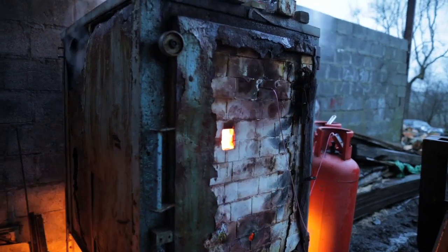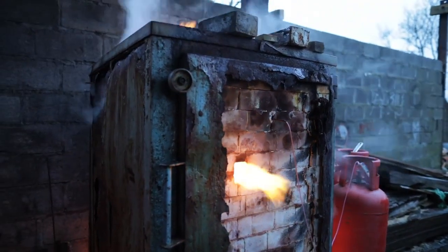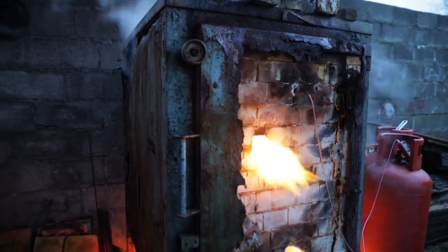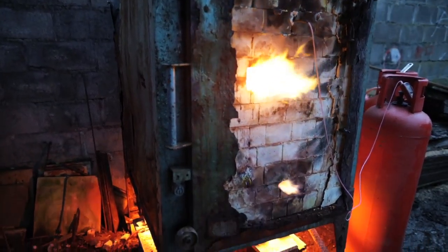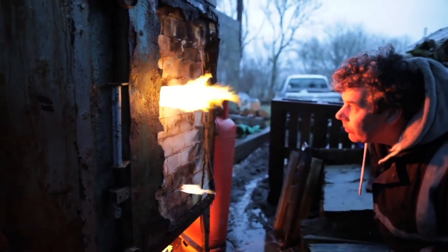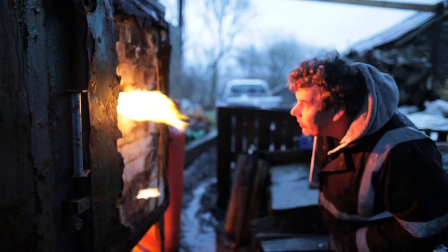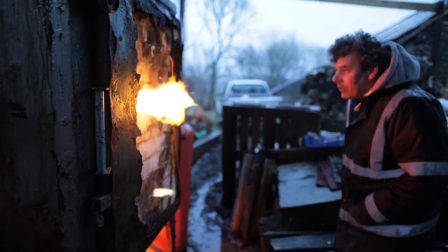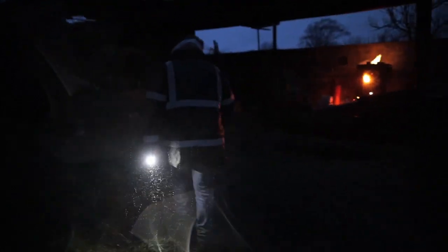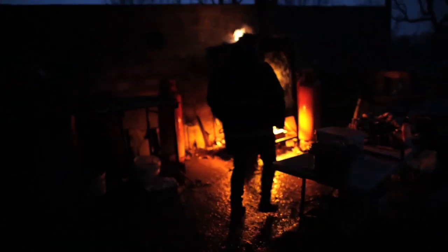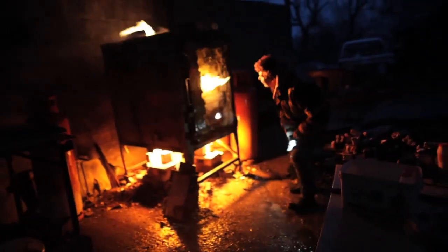Really, I'm doing a very fast firing, and when it's all dry and working properly, I can do the whole firing in 8 or 9 hours. After 600, I go full speed, building the heat up inside the kiln as fast as I can. When it reaches about 1260, I'll introduce the first lot of salt. I put in 1.5 kilos of salt in 4 batches over an hour while I hold it at the full temperature.